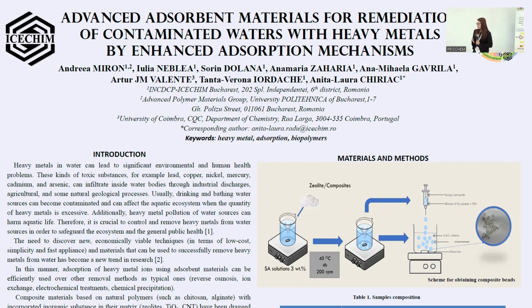The technology presented in this work is very simple, and we need just two steps. The first one is the homogenization of the zeolite in the polymeric solution, and after that the forming of the beads in a calcium chloride solution.